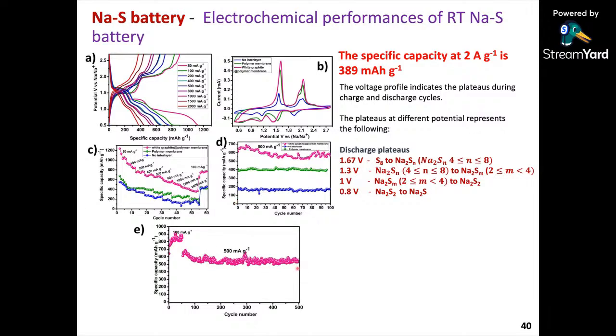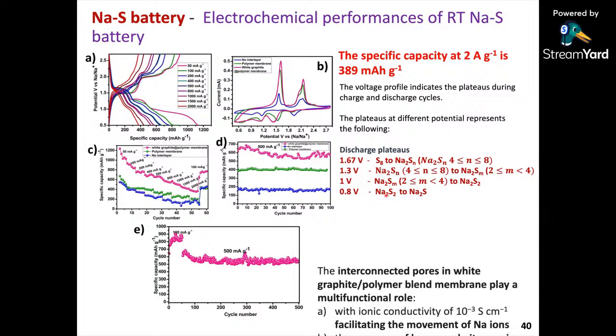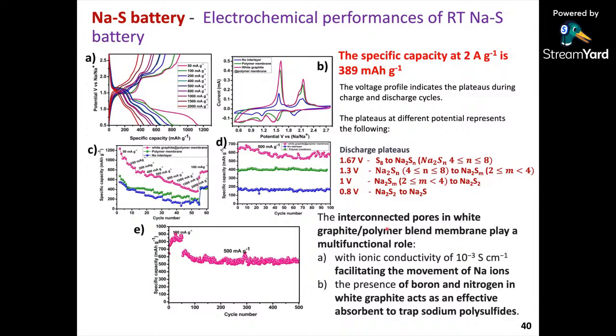considerably reduced. And then we have done it almost up to 500 cycles. We have got very close to 600 milliampere hour per gram capacity, and we have analyzed with reference to these plateaus, but I won't go into detail, and you can easily see that it forms these sodium polysulfides. Therefore, from the interlayer, you can easily see that interconnected pores in this boron nitride polymer blend increase the ionic conductivity, facilitating the movement of sodium ions, as well as trapping the sodium polysulfides, mainly because of the presence of boron nitride.